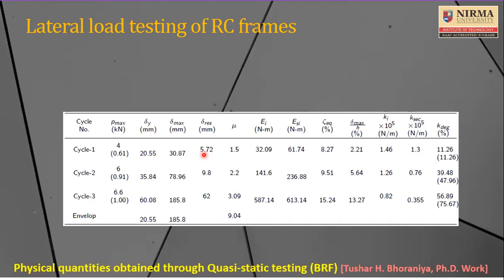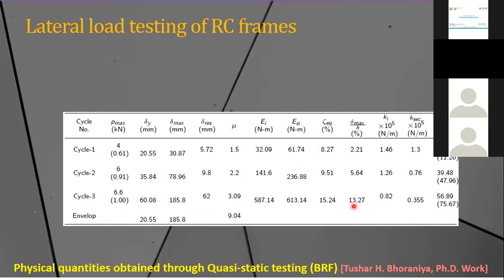And you can find out that the bare frame has a displacement ductility of the order of 1.5 for the first cycle and keeps on increasing, and overall displacement ductility is good, 9.04. In the same way the zeta value also keeps on increasing from around 8% to 15%, and delta max by H, that is drift, also keeps on increasing as you keep on applying the load horizontally, and the initial stiffness also keeps on reducing largely, from the value of 1.45 at the initial level to 1.25 and to 0.82, and similarly the degradation is also like 11% to 56%.